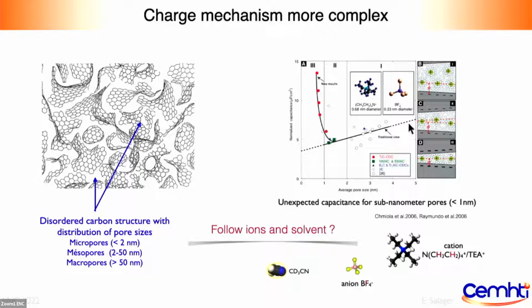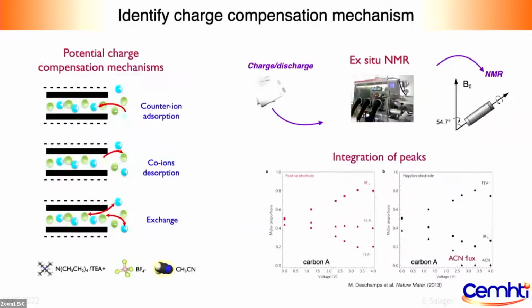So of course, this is a very interesting thing for NMR because the ions that we're using have NMR active nuclei, and we wanted to know more about what the ions do inside the supercaps. So there had been ex situ studies. In ex situ studies, you would charge and discharge a supercapacitor, bring it inside the glove box, scratch it, and measure it by magic angle spinning NMR. And so what could be shown is that for a negative electrode, so that's a pore, you have several ways to compensate for the charge. You can either have cations going in or anions going out, or both at the same time.